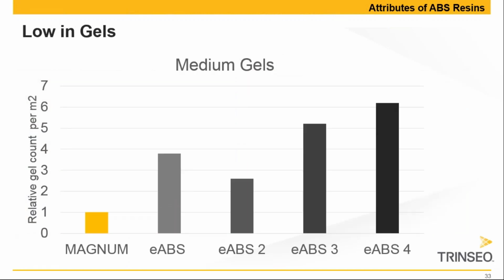Let's start first with the medium gels. I have here a relative count on the vertical axis per square meter of film. And for Magnum, that is obviously 1. And you see then that for the various emulsion ABSs tested, so the EABS is the high impact emulsion ABS, and then the 3 others are medium impact emulsion ABSs, there are about 2.5 to 6 times more medium sized gels that we found in these emulsion ABSs. So the risk for surface defects due to medium sized gels is significantly higher with emulsion ABS.